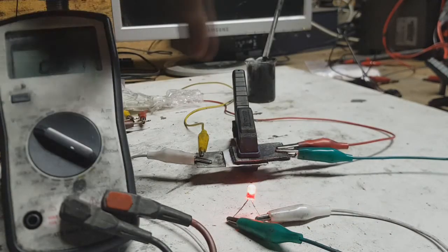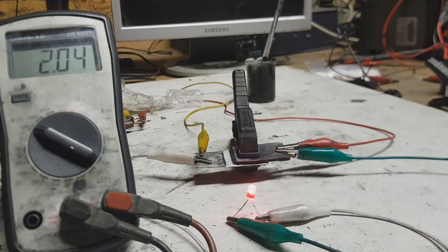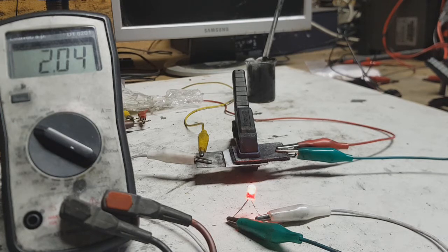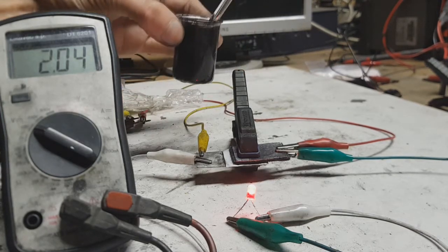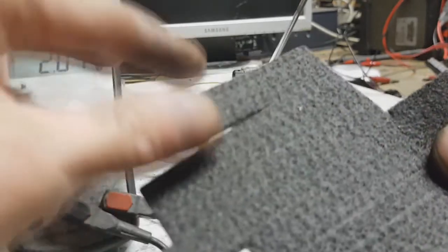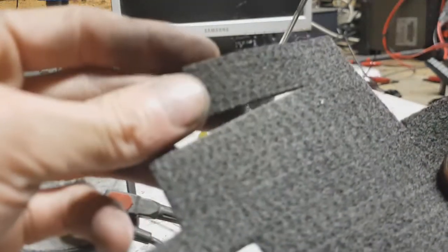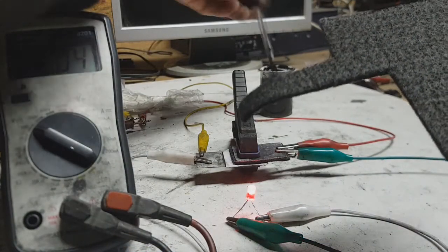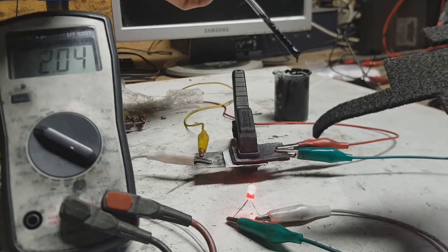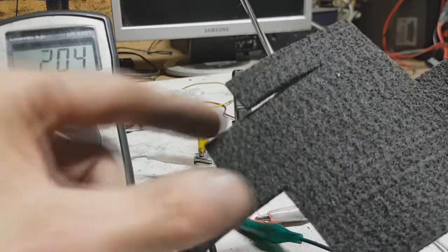The separator is the separator from lithium-ion batteries. And on the top I put this electrolyte on this carbon fiber. So I soak this acid electrolyte in this carbon fiber because this electrolyte is jelly-like, and the carbon fiber is really good for holding this gel electrolyte in place.